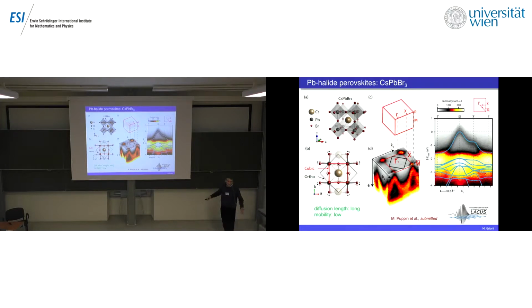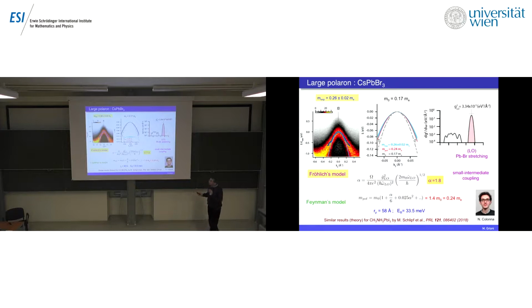Now you could say that the DFT calculation reproduces fairly well the result, but actually if one looks closer, there is a discrepancy. So this is a close-up of the maximum of the valence band. Here the points are fits to the spectral line shape that outline the band. From this fit, we can determine the effective mass. So here it's shown the effective mass from experiment is 0.26 times the bare mass of the electron, with some small error bar, and it's the blue curve. Now DFT would give you 0.17 times the electron mass. So there is about a 50% enhancement of the mass in the real system.